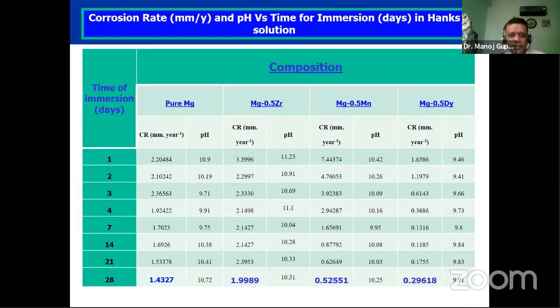Now, if you look at the rate of corrosion, because once the mechanical properties are qualified, then we have to look at how they corrode in a wet environment. So by putting in 0.5 zirconium, 0.5 manganese, and 0.5 dysprosium, you see that just 0.5 dysprosium can give you 0.29618 millimeter per year rate of corrosion. Manganese is also equally good because remember, in vivo you have to divide it by 4 or 5. So these two systems seem promising.